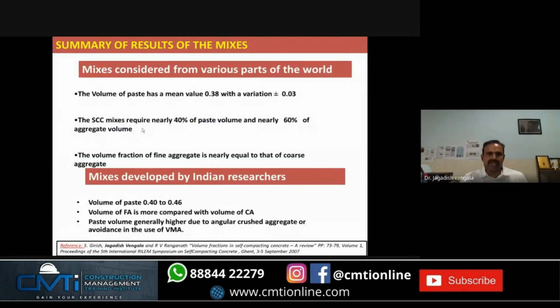So that's what SCC mix requires, nearly 40% of paste volume. But in the case of Indian researchers, you can see it requires 0.4 and above, 40% and above. This is due to angular crushed aggregates. Otherwise, if you want to avoid viscosity modifying admixture, you need to put more paste into the system.